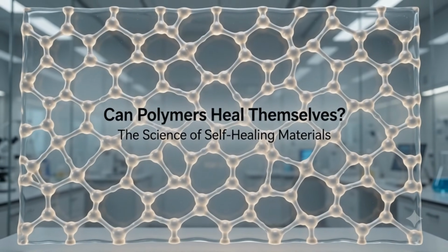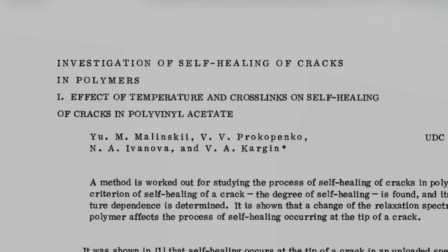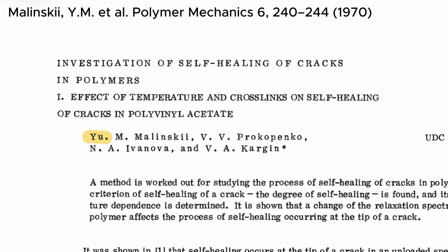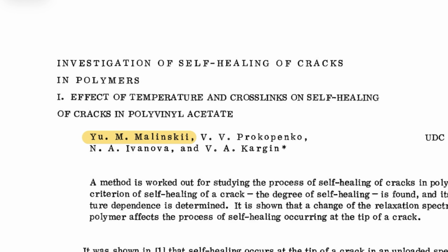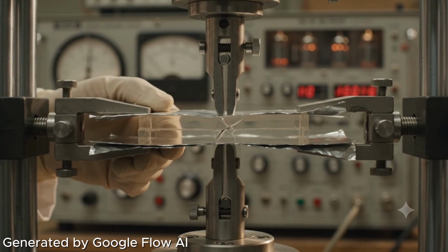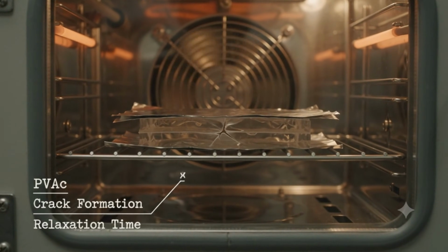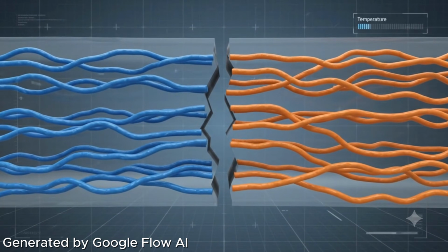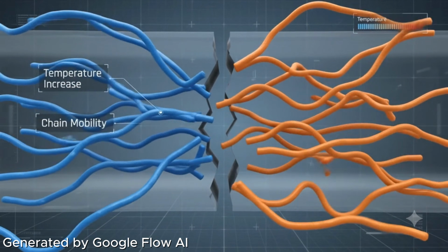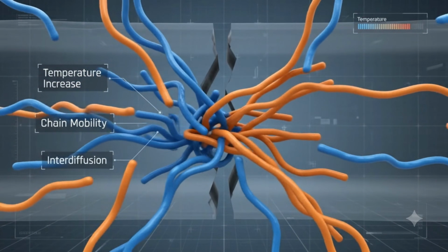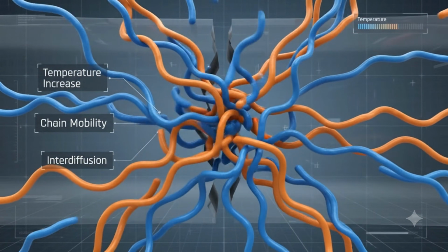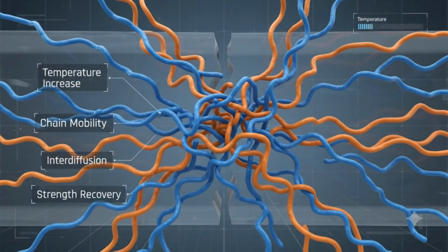Can polymers heal themselves? Discover the science of self-healing materials. The term self-healing in polymers was first introduced by Malinsky and his colleagues in the early 1970s. In their pioneering study on polyvinyl acetate, they created cracks in polymer samples and observed how the material recovers strength after being left at elevated temperatures. As the temperature approached the glass transition temperature, polymer chains became mobile and diffused across the crack interface. This molecular interdiffusion gradually reconnected the material, leading to partial recovery of mechanical strength.